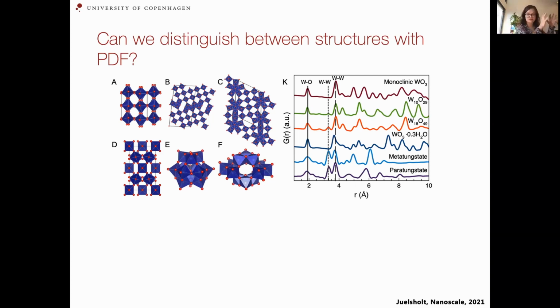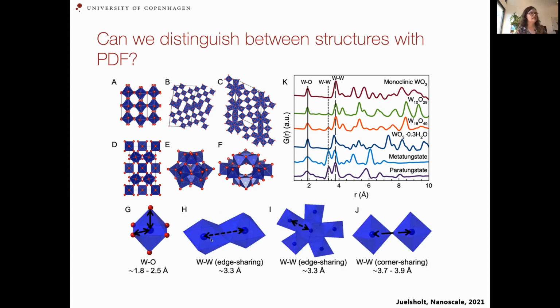So we had these tungsten oxide structures, and we can look now, if instead of being in Q space, in scattering space, can I actually distinguish between the structures in R space? So here I have some of these structures that we were looking at before, the monoclinic tungsten oxide and different stoichiometries here. And the PDFs are represented here. The first peak in these structures will be a tungsten-oxygen distance, because that's basically always going to be the same distance, between a tungsten and an oxygen atom. Then we're going to have different peaks out here. The second peak here is a tungsten-tungsten distance in edge-sharing octahedra, as we have them here or here. And then the next one is in corner-sharing octahedra.